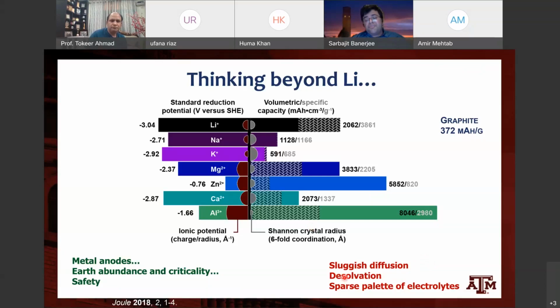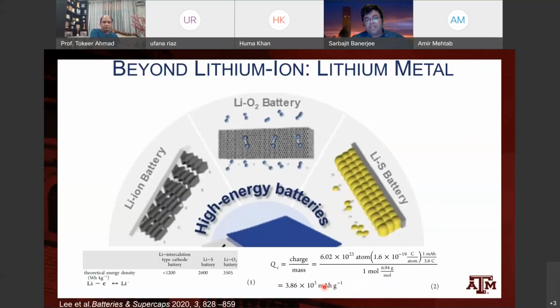There's challenges further with developing good electrolytes that allow for ions to be readily desolvated. Again, breaking the bond between the lithium cation and an anion is relatively easy. At the interface, this becomes a lot harder for divalent cations, and this is really responsible for relatively sparse available electrolytes.